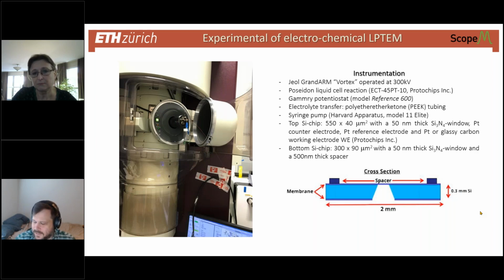That's an interesting technique that I actually hadn't seen, using STEM to move a bubble that forms in the cell. But that's one of the things that comes up when you're doing in situ liquid, especially a gas generating reaction: how you deal with the gas. You have to do something, otherwise a lot of hours of preparation is just nothing, right? If you have a bubble. That's the same. It really helped, not every time, but quite a decent way. You just don't shoot in the center of the image, of course, but good.